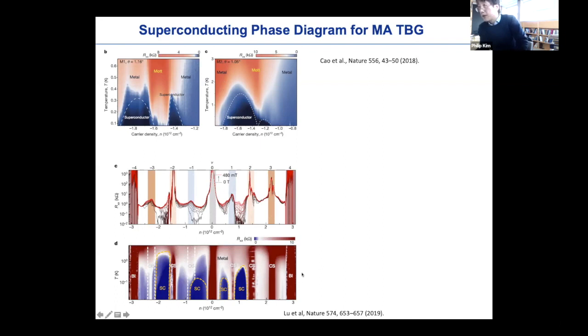Now, a few months later, about a year later, this is the state of the art of the sample prepared by Dmitri Efetov's group that Alan showed. The phase diagram is now a little bit different. Not only the one insulating regime that they originally studied, but the superconductivity appears next to many of these other types of correlated insulating regimes, not only at half filling but also quarter filling and three-quarter filling. There's also an insulating regime, and nearby that insulating regime, if you go low enough, superconducting-like states appear in this type of sample.